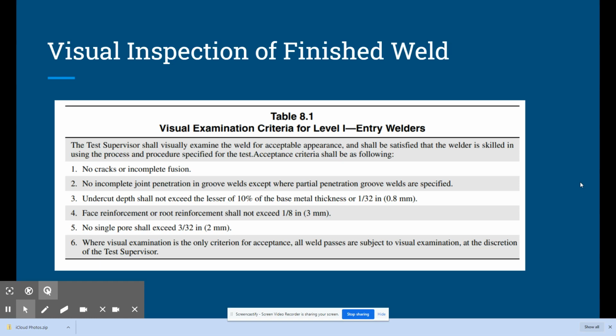Number 5, no single pore shall exceed 3/32. So we're talking about porosity. Every once in a while, you get some porosity with stick welding. Oftentimes on a restart where it's cold, you might have some porosity. You're allowed porosity. You're just not allowed porosity that's bigger than a 3/32 diameter. So we'll look for porosity as it shows up.